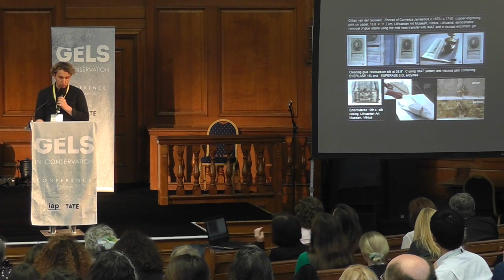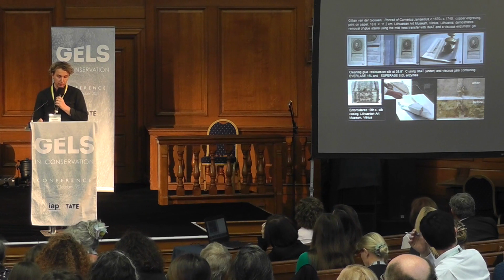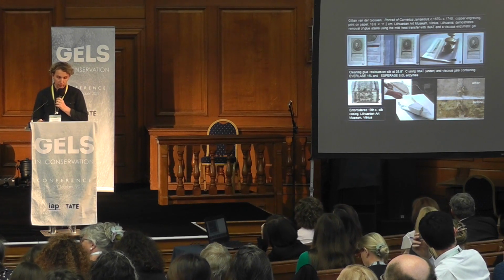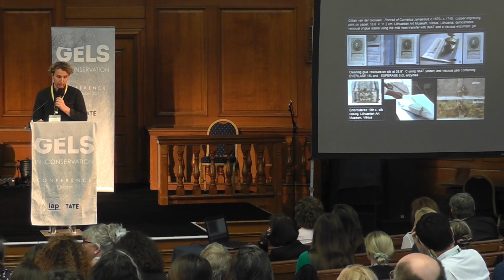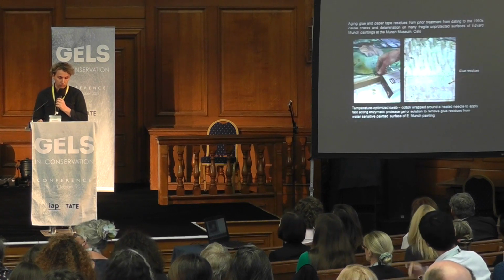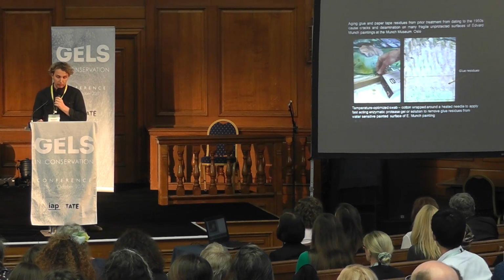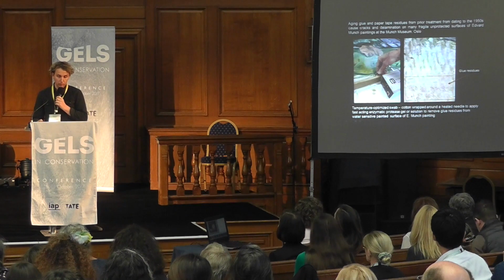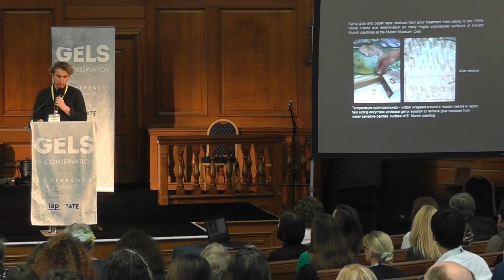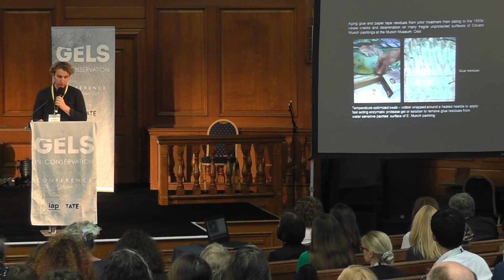A similar approach below was applied to clean glue residues from textile using Everlase 16L and Esperase 8.0L. Temperature modulation was successful, removing glue residues on fragile surfaces of Edvard Munch paintings. Heat transfer allowed a substantial reduction of application time and made possible the removal of glue residues from water-sensitive surfaces.